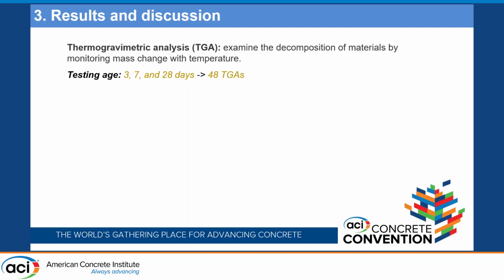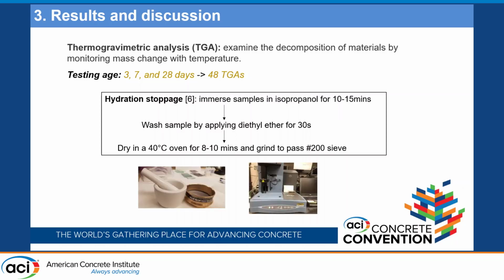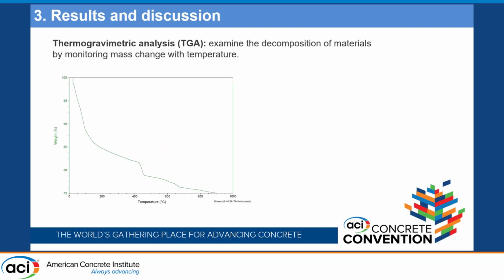We did that at 3, 7, and 28 days. We used the procedure that is described here. We stopped the hydration at a certain age by using isopropanol, and then we crushed the samples, dried them briefly, crushed them again, and performed the analysis in the TGA instrument.